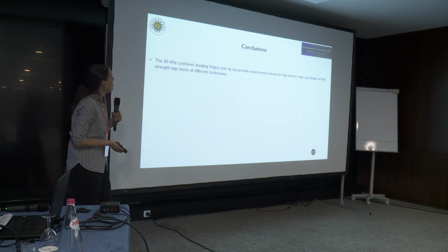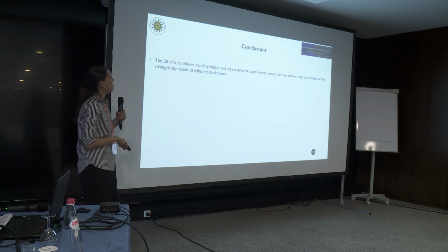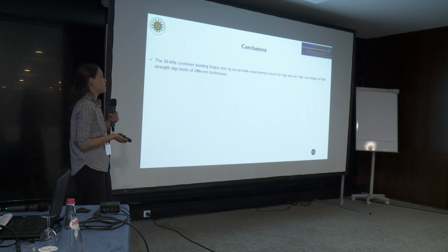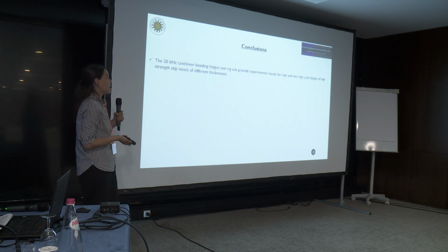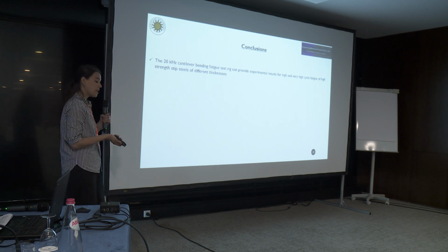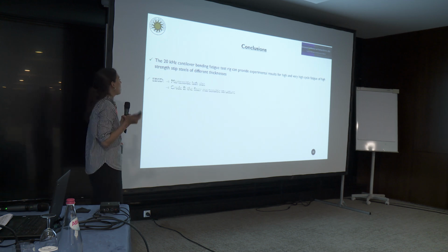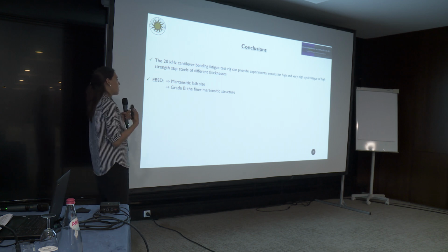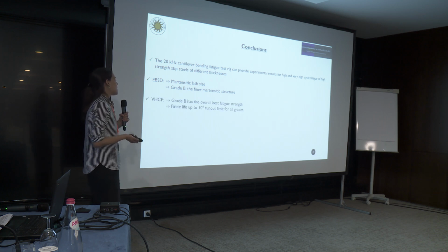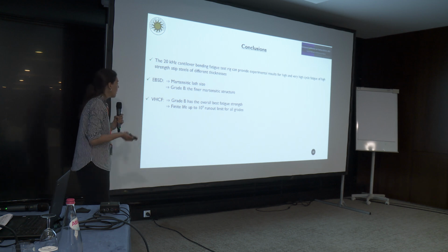So to sum up, the 20 kHz cantilever bending fatigue testing can provide experimental results for high and very high cycle fatigue of high strength steels of different thicknesses and properties. The EBSD analysis was used in order to have an image of the martensitic grain size, and we saw that grade B has the finer martensitic structure. The very high cycle fatigue testing gave us that grade B has the overall best fatigue strength, and that we can have finite lives up to 10^9.